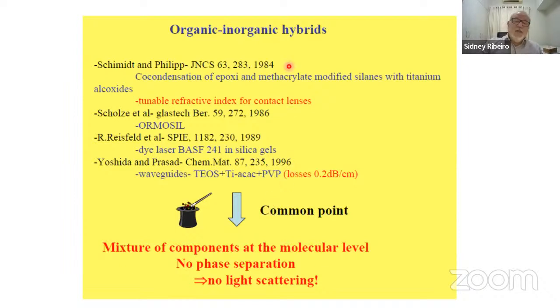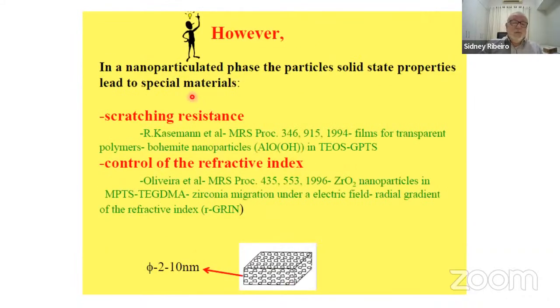So we have here in the 80s, after the proposition of this kind of materials by Professor Schmidt, some papers became very famous with different applications. But the common point that must be cited here is the mixture of components at the molecular level. There is no phase separation, so no light scattering, good optical property. However, we must say that in a nanoparticulate phase, the particles' solid state properties are kept and lead to special materials. For example, the scratching resistance that we have in our glasses today, the control of refractive index, the local control of the refractive index, for example, where particles can migrate under an electric field. These are the so-called GRIN lenses.